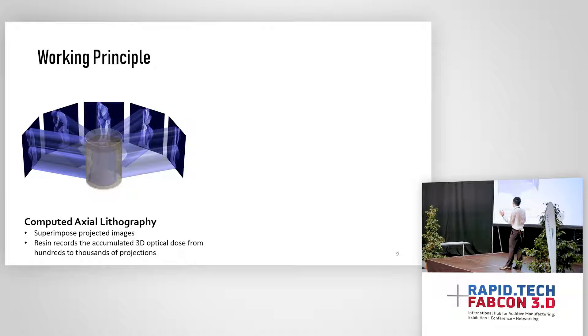The resin records all those projections and accumulates the optical dose. Material that receives a really high optical dose will solidify and convert. Those that are underexposed can be washed away. I can show you more with the following video.